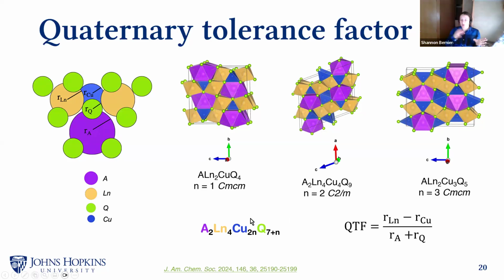They crystallize into 3 different structures that have different bonding arrangements. So 2 of them have the same space group, i.e. the same overall unit cell shape. They're both orthorhombic. This is the n=1 variant, n being the values here in this equation, and the n=3 variant. And then the n=2 variant is actually a monoclinic structure where there's a change in the angles.